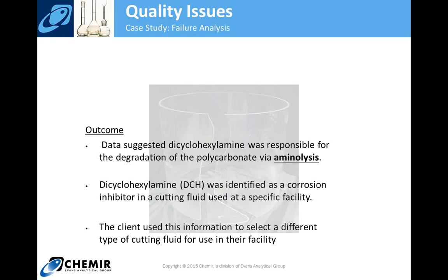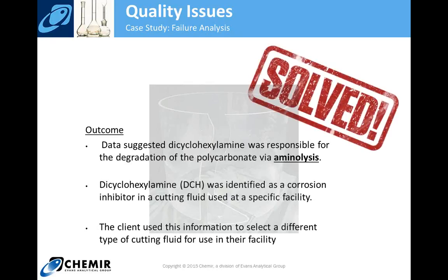And another end result is that the client, this metalworking facility, was able to identify different cutting fluids, different corrosion inhibitors, things that didn't impact the polycarbonate. So it was a relatively easy fix for their client, and again, just a different end result from this root cause analysis. And this case was solved. It gets the rubber stamp there that this was solved.